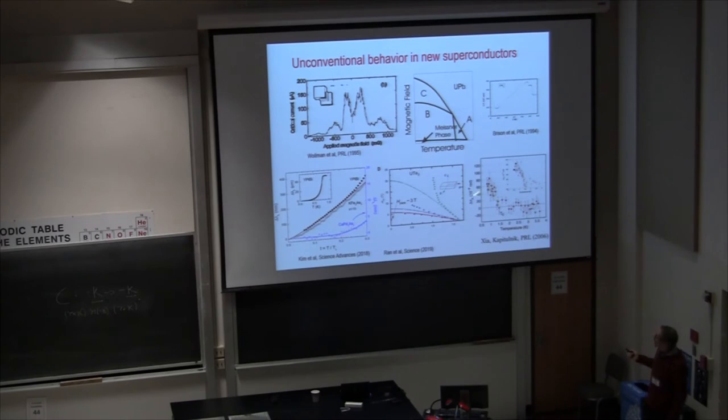And what this change in polarization means is that your superconductor is breaking time reversal symmetry. There's some magnetization associated with the superconducting state. And that's very puzzling because we already expect from conventional superconductors that they're going to expel all magnetic fields. So where on earth is such a magnetization coming from?